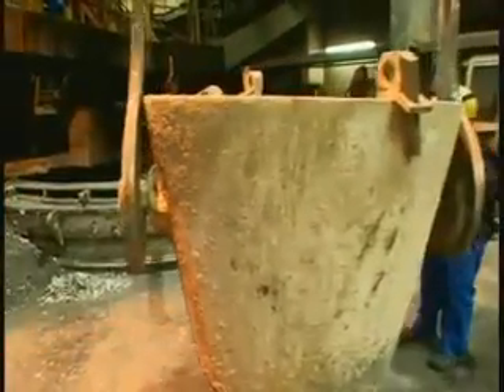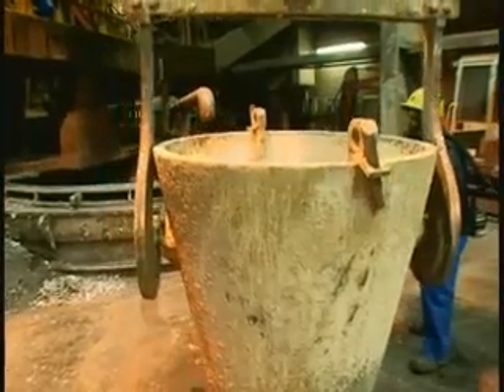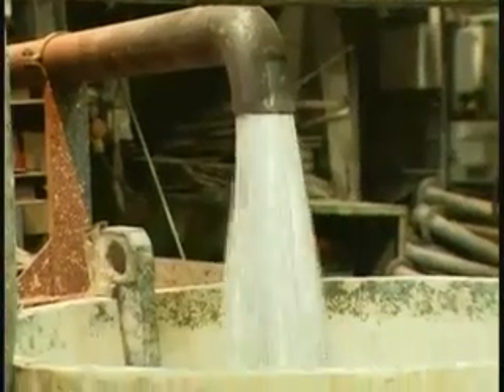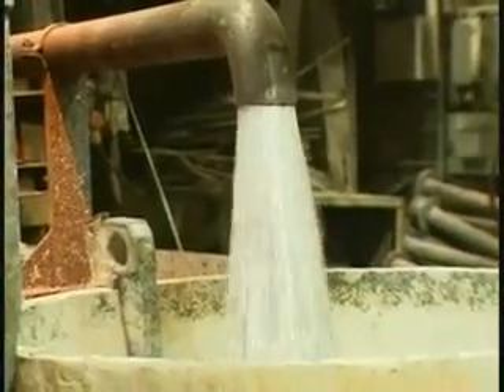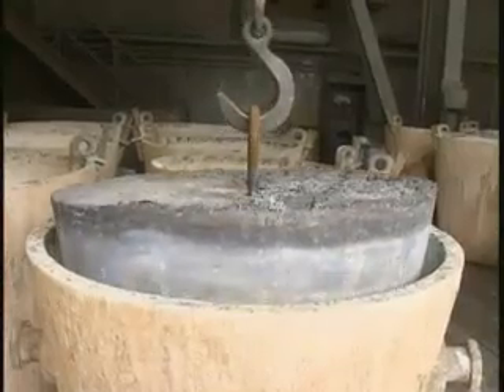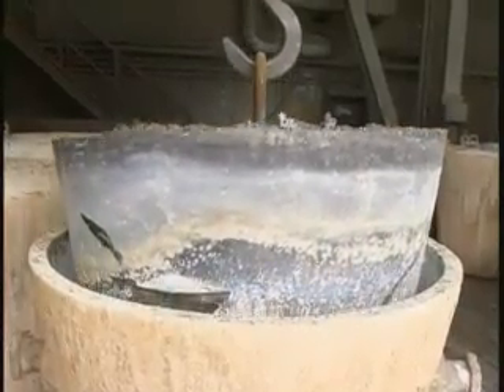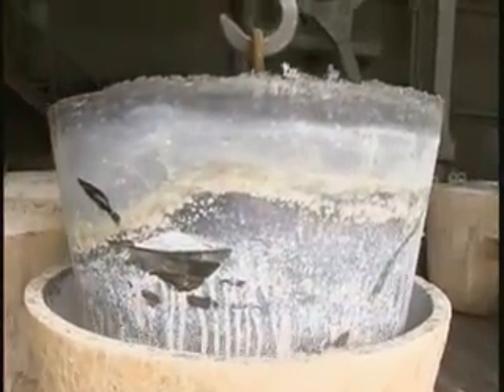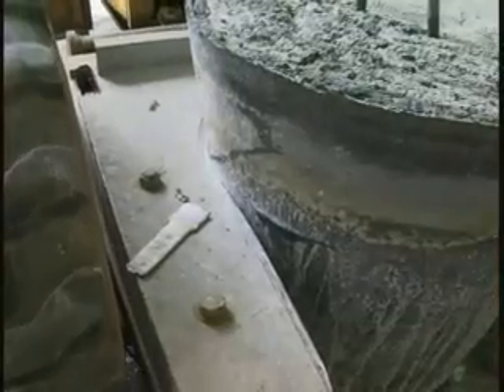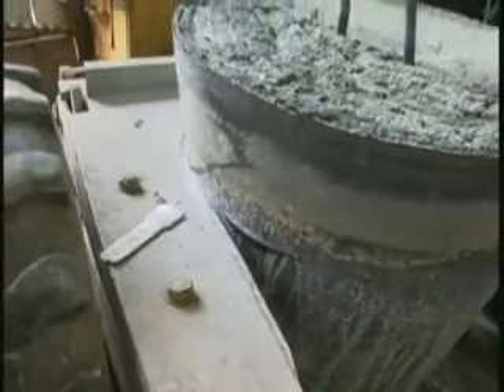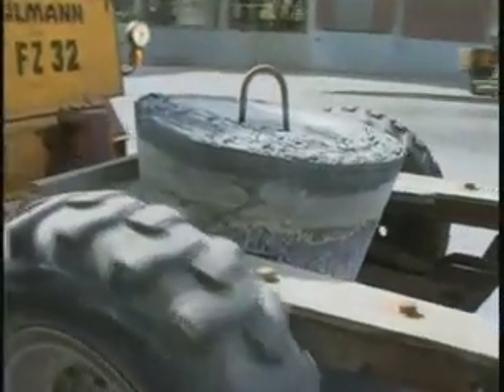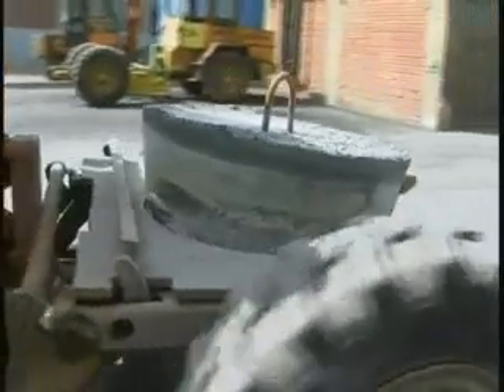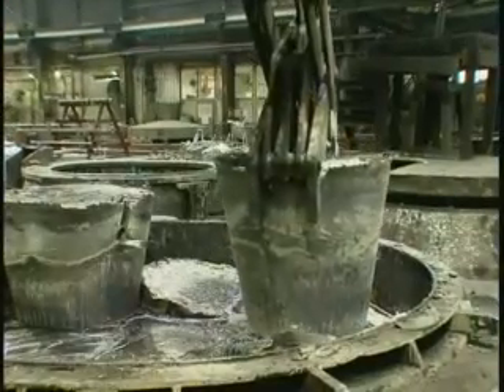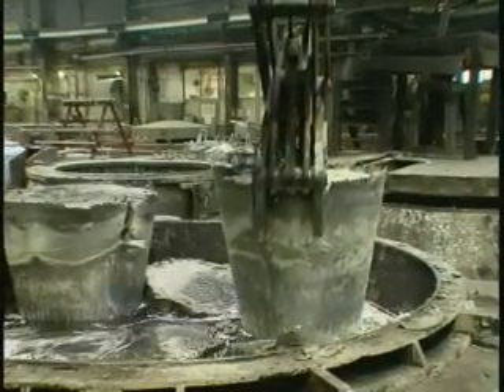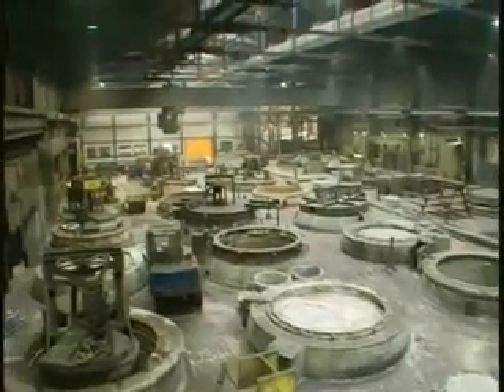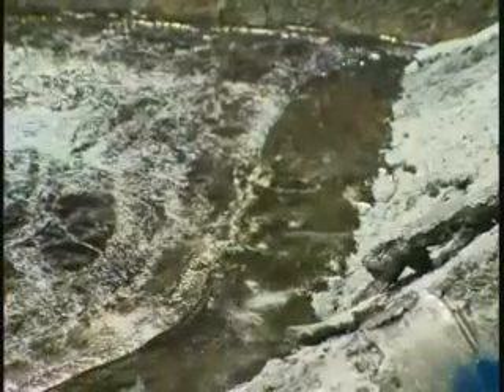The lead bullion produced in the QSL reactor is not a pure product yet, but still contains metallic impurities like copper, silver, gold, or bismuth. In order to remove these impurities, the bullion, weighing tons, is transported to the refining unit, where it is freed from impurities step by step. For this purpose, it is first melted again. Then, stepwise, one impurity after the other is eliminated from the liquid lead.